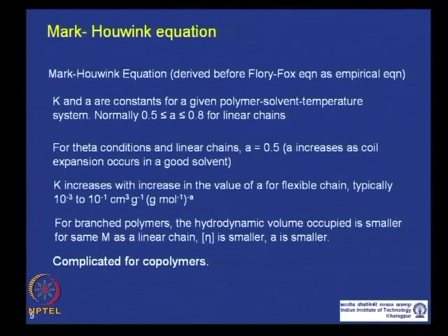Now, A increases as the coil expansion occurs in good solvent. In good solvent, the coil expands. So, the value of expansion factor becomes more than 1. So, the A value becomes more than 0.5. Now, K increases with the value of A for flexible chains. Typically, it has been seen that K also increases with the increase in the value of A, and it is typically around this range.